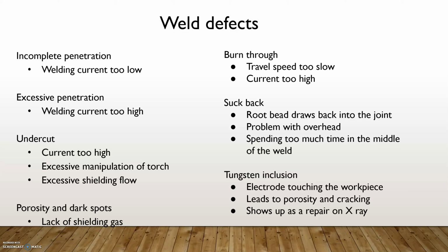And tungsten inclusions, that's from your electrode touching the workpiece. This leads to porosity and cracking. A tungsten inclusion will always show up on an x-ray, so if you ever touch your tungsten to the work, it's good practice just to stop and grind that part out. Go resharpen your tungsten and start again. But we'll practice all this in the shop, of course.